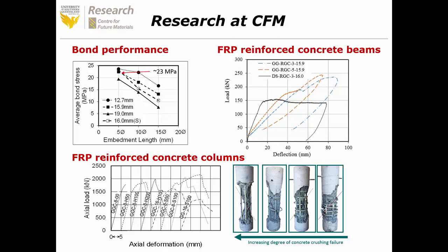The behavior of concrete beams reinforced with FRP bars also showed us that by effectively designing concrete beams reinforced with FRP reinforcement, we can achieve higher strength concrete beams using the same amount of reinforcement, and we can also achieve a pseudoductile failure behavior, which is important in structural engineering because this behavior provides a warning of impending failure of the structure.